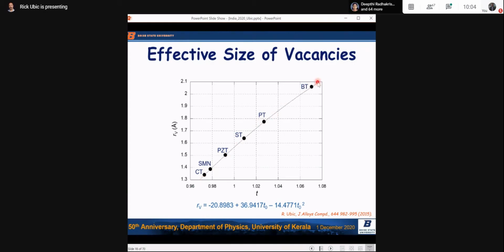In all of these, the A site vacancy is larger than the A site cation it replaces, which means the cation vacancies have a pushing effect. So far from being the size 0, they actually look like they're bigger than the cation they replaced, right? You get repulsion. You think about that, you take a cation out. The cation was coordinated to anions, which now just see another anion across the vacancy, right? And so they repel. And it looks like something big is between them because of the charge. All right.